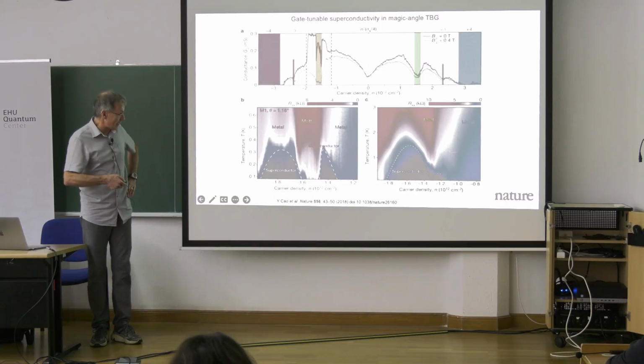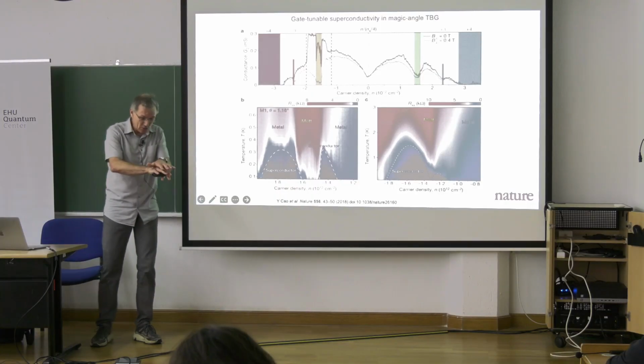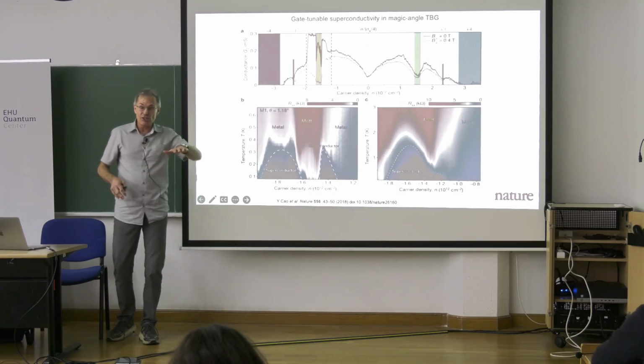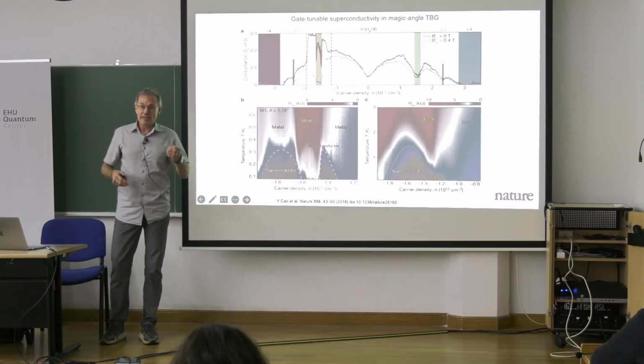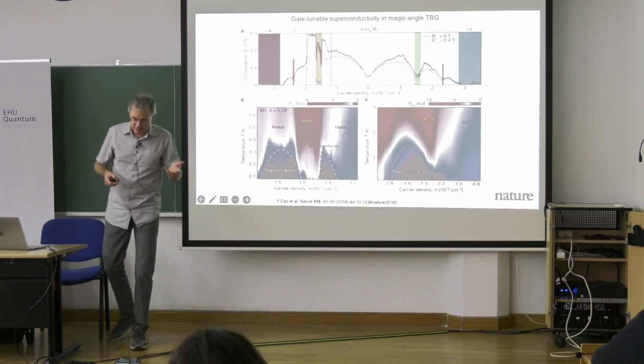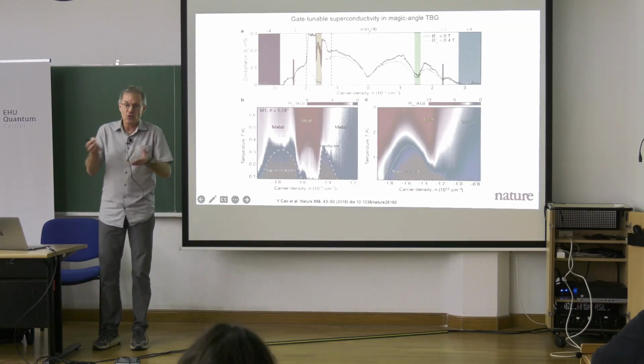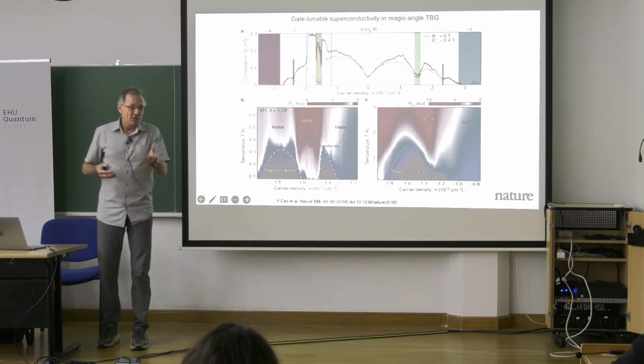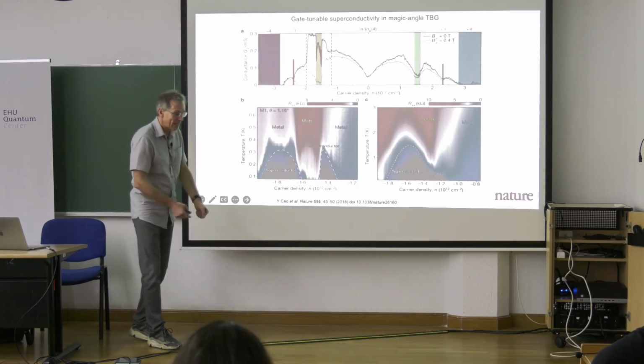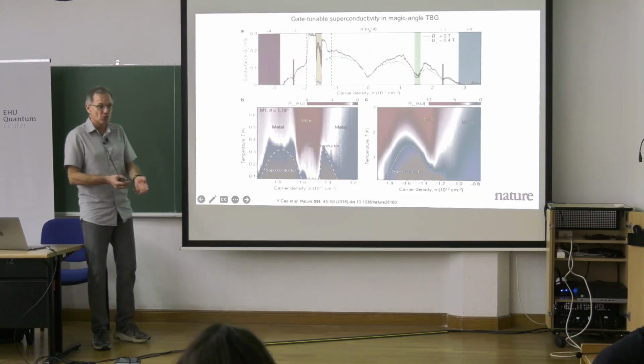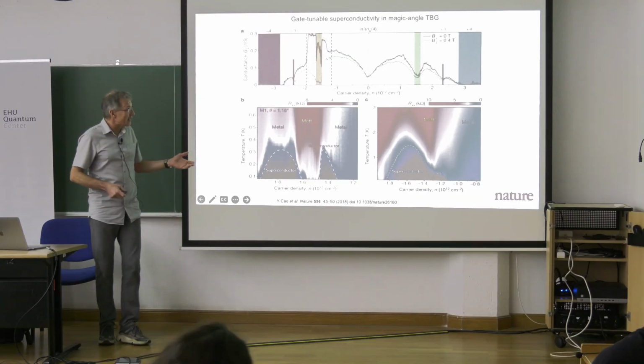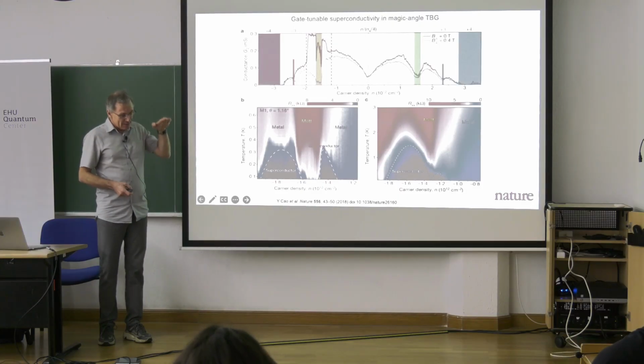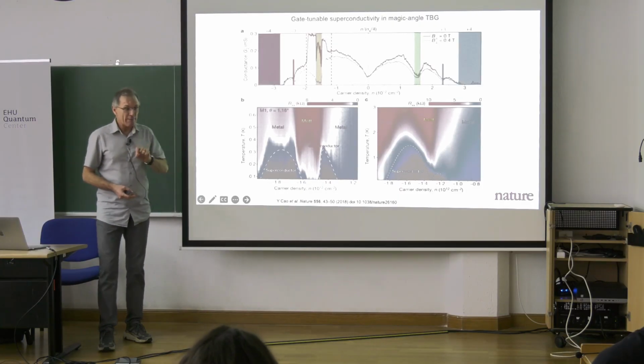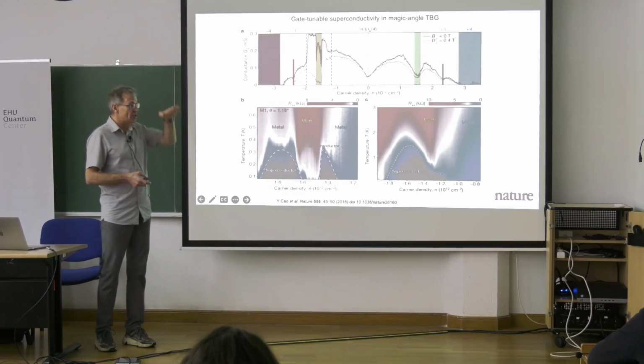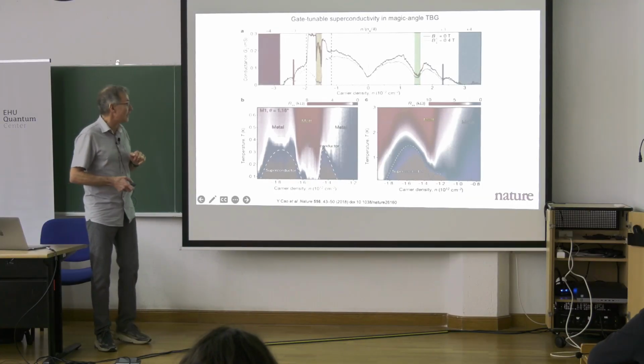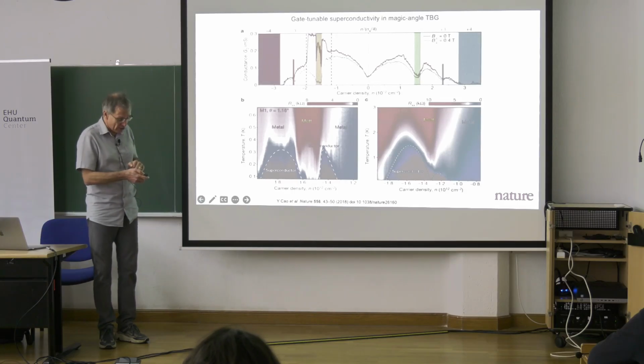And what is good in this twisted material is that you can change properties, which in other materials is done by doping. Well, in semiconductors, like a p-n junction, when you dope, our modern electronics is based on doping, and usually you do it chemically. Here, you apply voltage to your sample, and voltage changes the occupation, changes the number of carriers, and as a result, you change all properties.